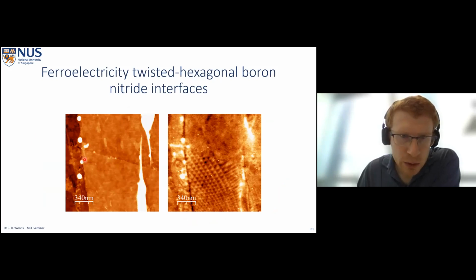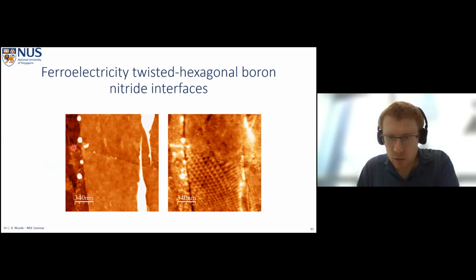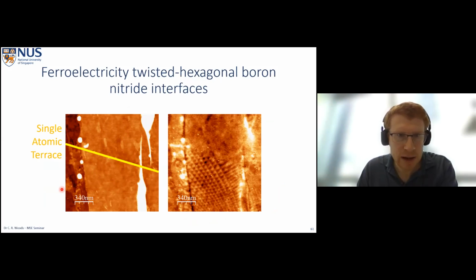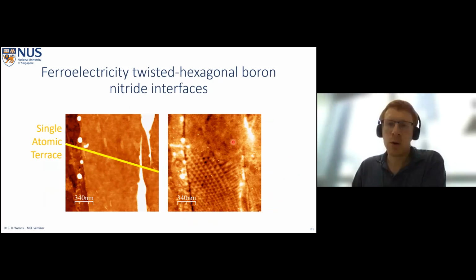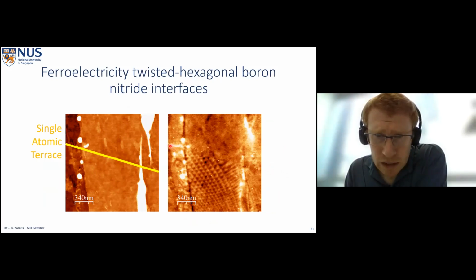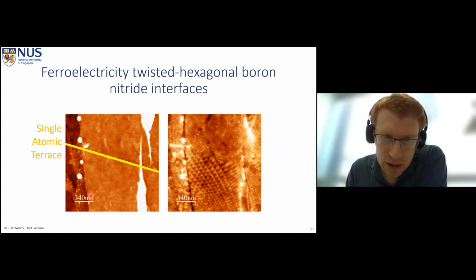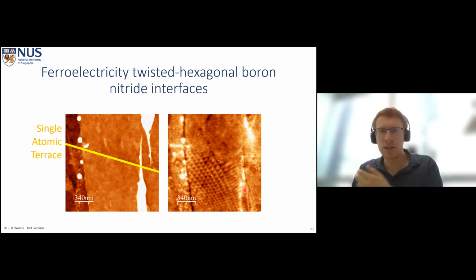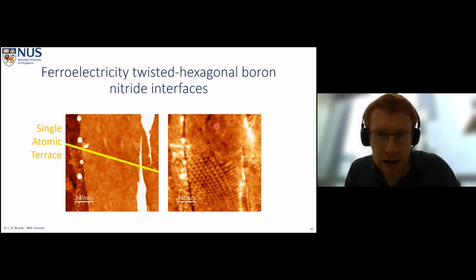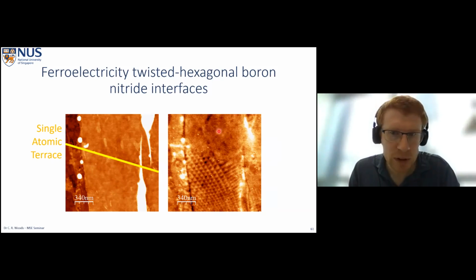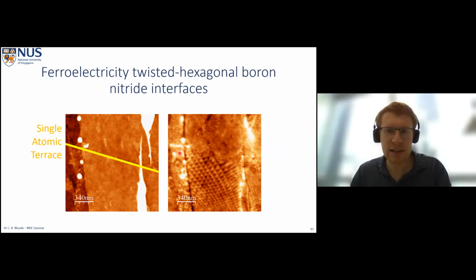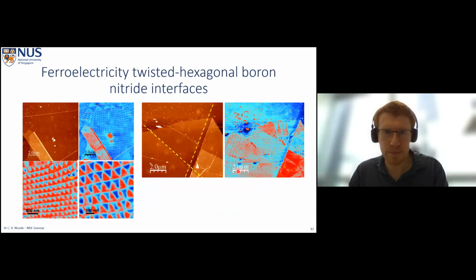So on the left, you're looking at just an AFM topography image of our flake. This is the edge of our top boron nitride. And running through the middle here is our single atomic terrace in our bottom boron nitride. And on the right-hand side, you can see our EFM signal. And what you can see is that we have this very regular periodicity in the EFM signal, which doesn't exist in topography, and it cuts off exactly where the monolayer step is. So this is a really good indication that we have anti-parallel or parallel on one side of this monolayer step, whereas parallel or anti-parallel on the other. So we have the inversion across the monolayer step, and we're seeing something really interesting for one of these configurations.